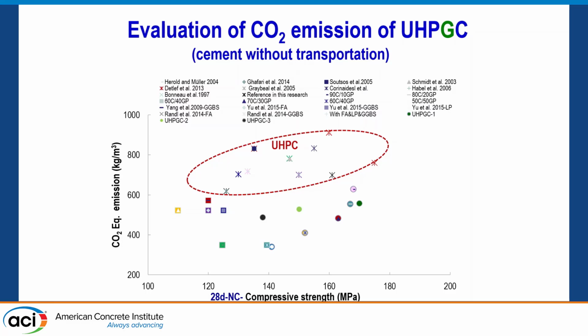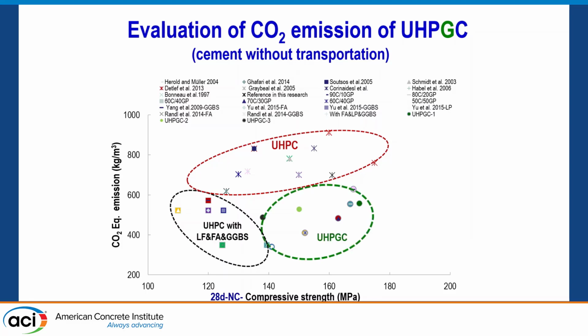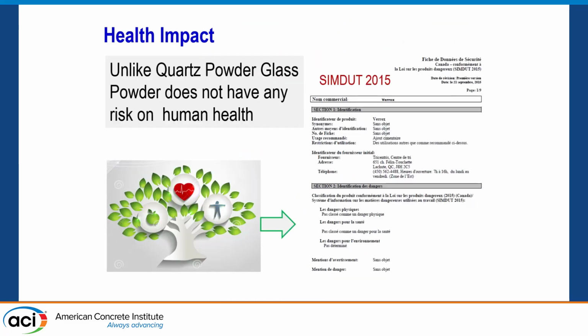You can see here the high quantity of CO2, and you can have a large range of compressive strengths. But when you go for replacement with the other materials, you can see here, of course, you decrease the CO2, but you have to optimize better if you want to have a higher compressive strength. And those are our UHPC with glass powder, where the rheology, the fluidity was good, the compressive strength was good, and the CO2 emission was decreasing, of course, because we are replacing a lot of particles there. So, as I told you, this is not me who is telling that about the quartz, so be careful.